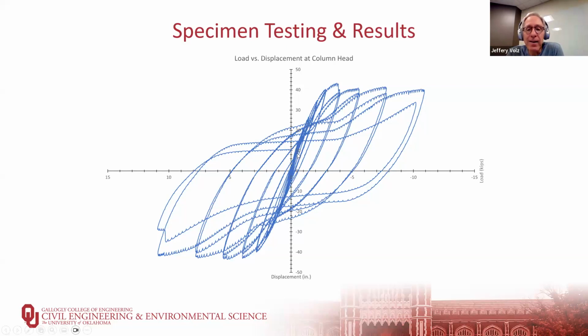So if you look at, let's say, the very last cycle, you see the capacity is very low here. What's happened is we've buckled the part of the tube that's in compression. So when we were placing it in compression over here, it buckled, and then we started to go back in the other direction. Now, here it's in compression, we bring it back to zero, we start putting that buckled section of the steel tube into tension. What happens when you place that buckled section of the tube in tension?